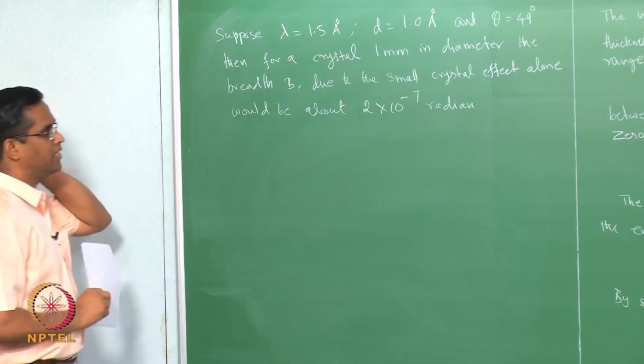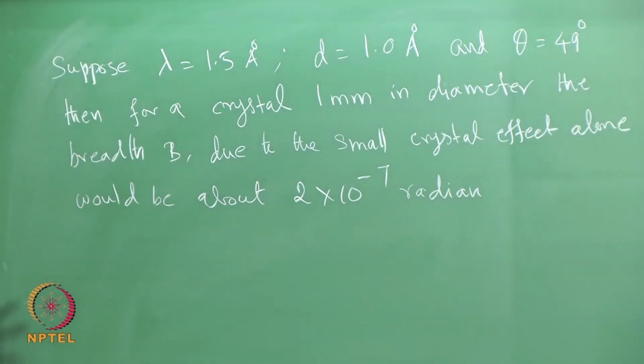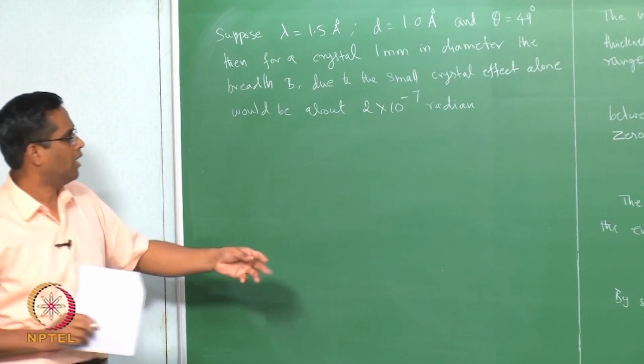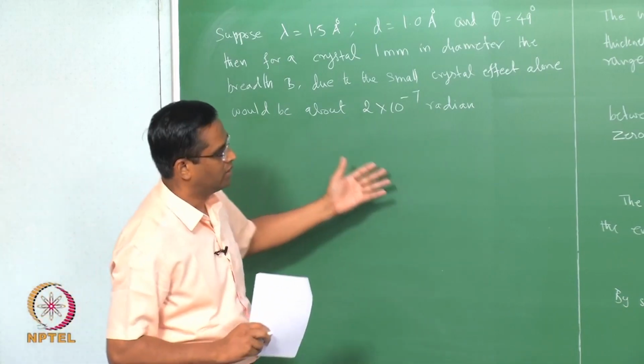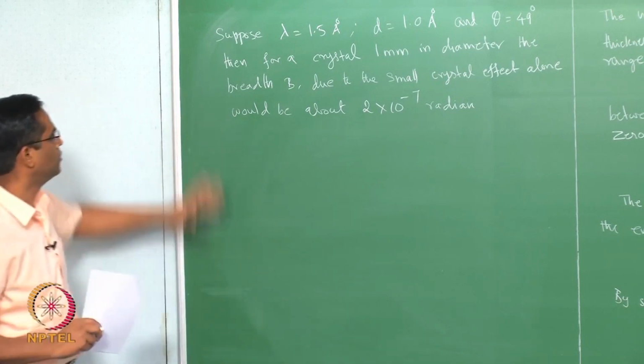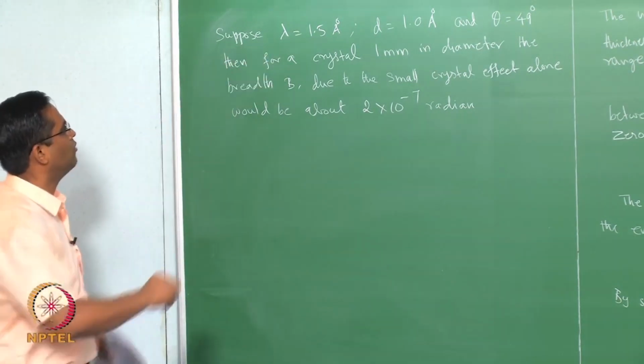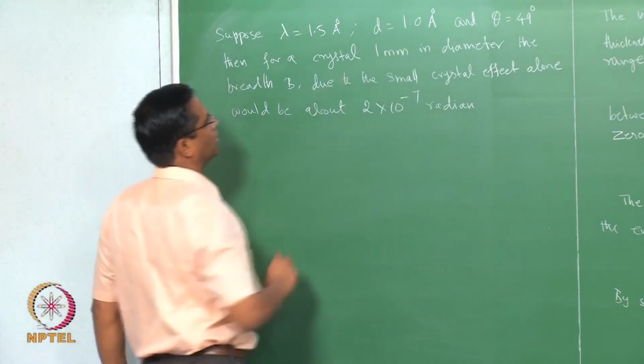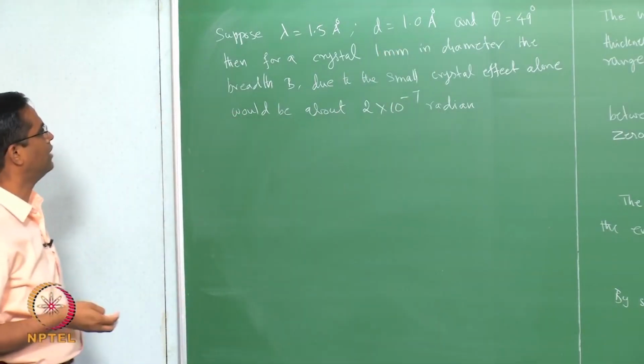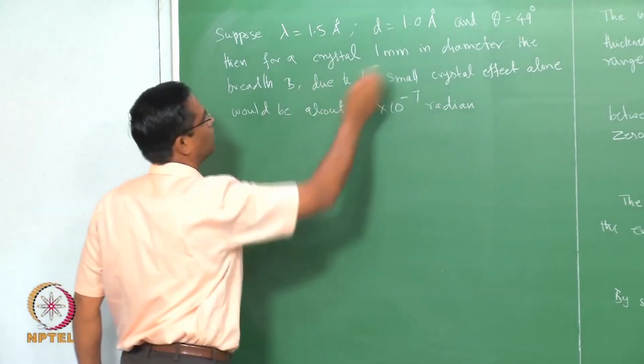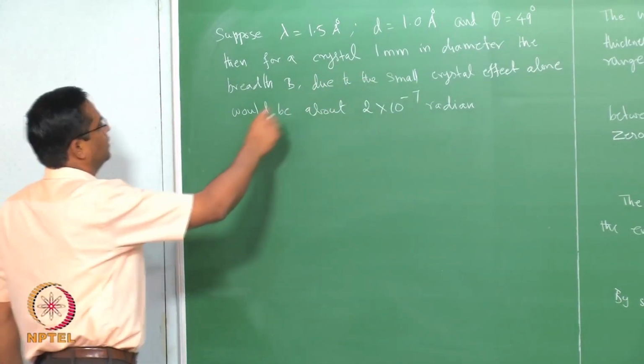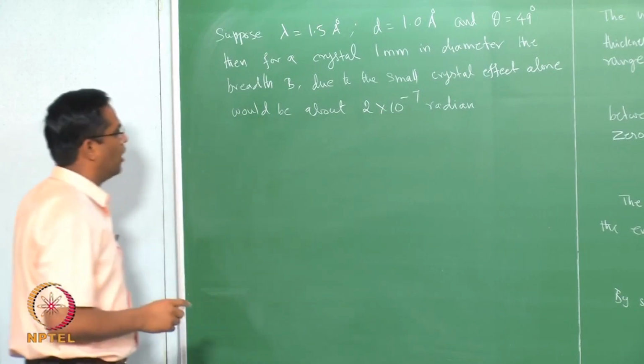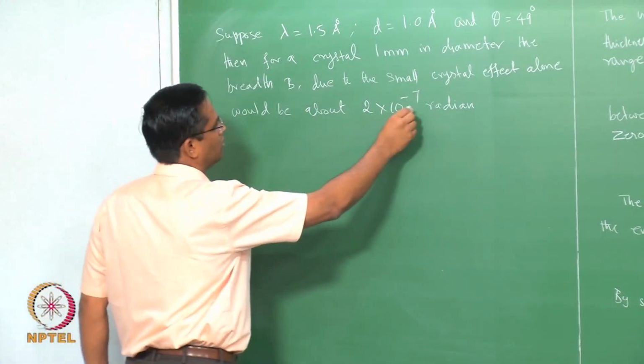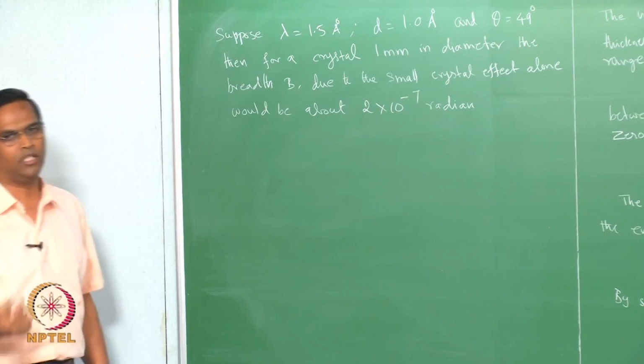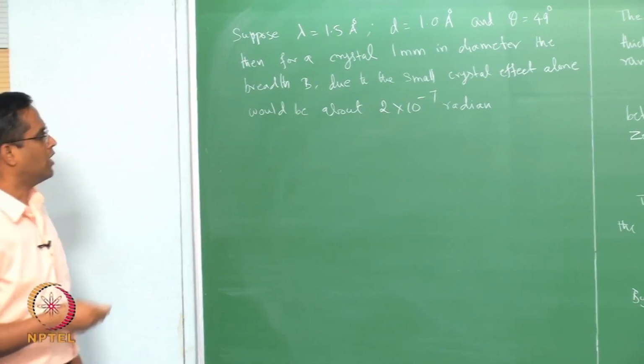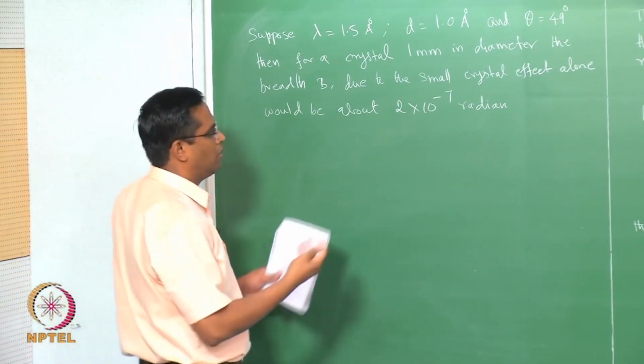So, what I am trying to say is what is that crystal size effect which will be having some visible effect on this peak broadening. Suppose if you assume that lambda is equal to 1.5 angstrom, d is 1 angstrom and theta is 49 degree, then for a crystal 1 mm in diameter, the B due to the small crystal effect alone would be about 2 into 10 to the power minus 7 radian. It is going to be extremely small. So, what is the size we will be able to see appreciably?